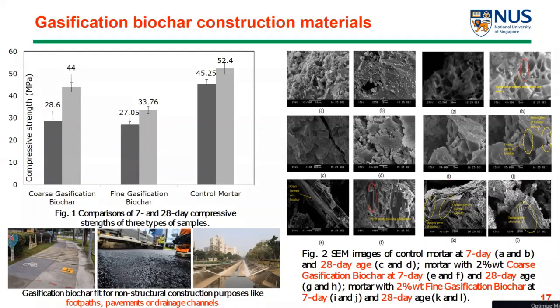As Liu Ming explained, this biochar may be heavy in heavy metals. I mean, a large quantity of heavy metals would be present. So that may be the cause of the lower strength. Then Figure 2 shows the scanning electron microscopy images of control mortar at 7-day, A and B, and 28-day age, C and D. And then, of course, mortar with 2% weight of coarse gasification biochar at 7-day and 28-day age, and mortar with 2% weight of fine gasification biochar at 7-day and 28-day, respectively.